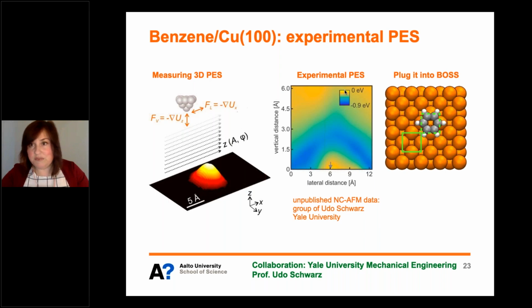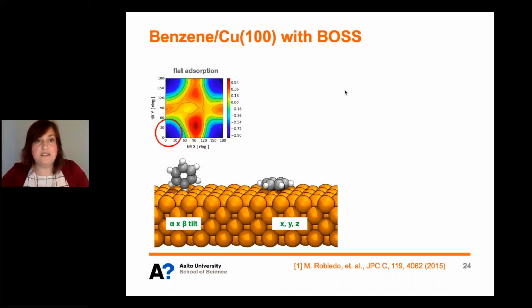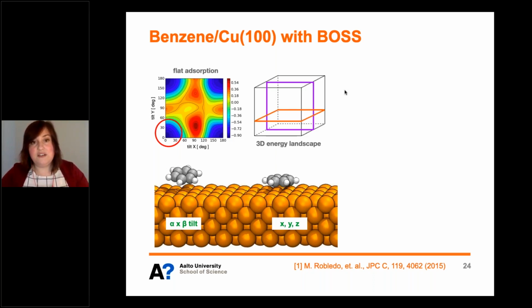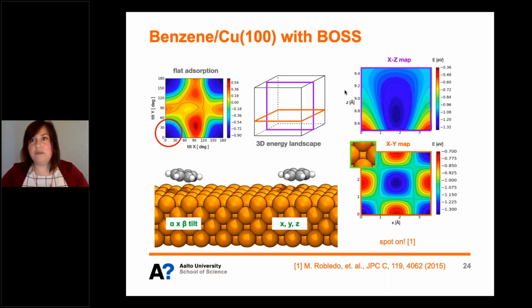So we thought to maybe just plug the system into BOSS, because benzene is really easy for building blocks, and see what comes out. When we looked at the system, we first checked the rotational angles, and indeed we found that flat adsorption is preferred. So then we just forgot about rotation, and we did a 3D energy landscape in X, Y, and Z. And this was particularly useful because you can cut it in different two-dimensional cross-sections that give you some chemically meaningful information about the system. If you look at the XZ energy map, you can really identify the spot where the molecule likes to adsorb. And if you look top down on the XY map, you can see the global minimum is above this hollow site on the surface, and then the bridge is a saddle point, and then the atoms are maxima.